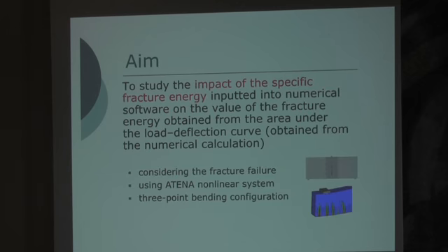So our aim was to study the impact of the specific fracture energy input into numerical software, and the dependency on the value of the total fracture energy obtained from the numerical results. We wanted to consider the fracture failure of the test specimen, so we chose a commercial nonlinear software which can predict quasi-brittle fracture. It's called ATENA 2D, and we chose the test configuration of